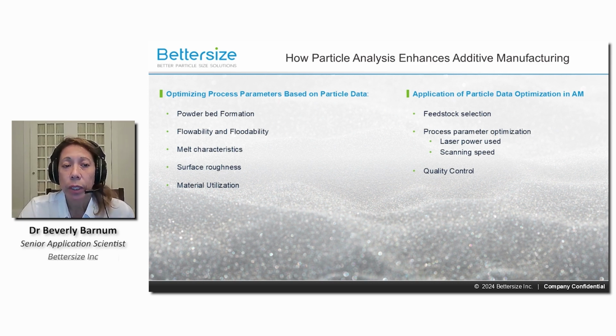By choosing the right powder with the optimal particle size and shape for the desired application, we consider factors like strength, density, and surface finish of the final product. By adjusting the processing parameters like the laser power and the scan speed based on the particle characteristics that are known, you can achieve optimal melting and fusion during the process. And by regularly monitoring particle size distribution to identify potential issues in the powder feedstock, this allows quality control to maintain consistent quality.